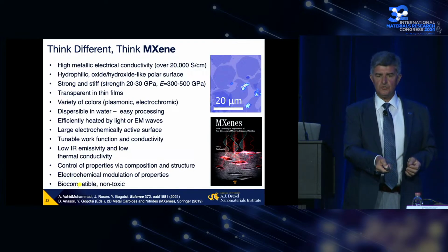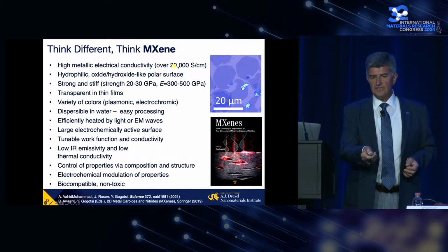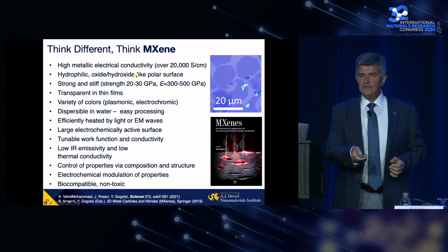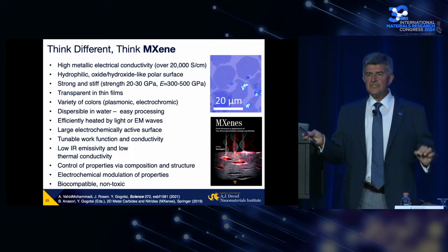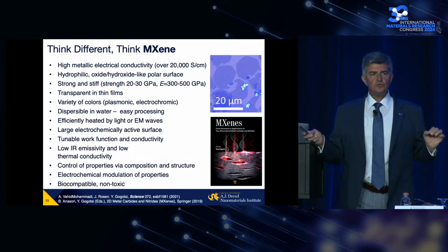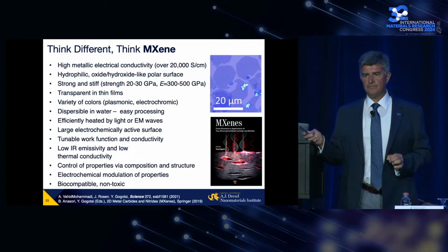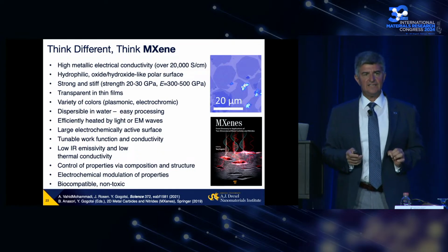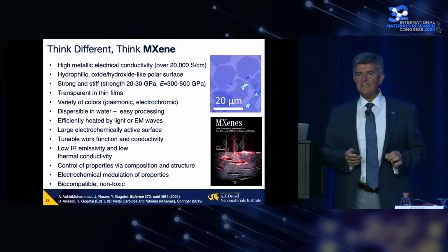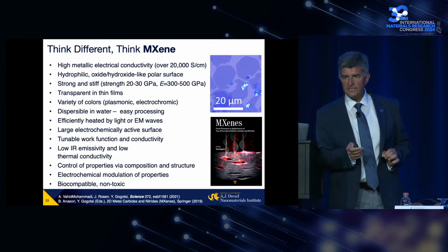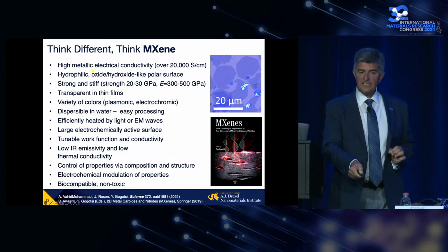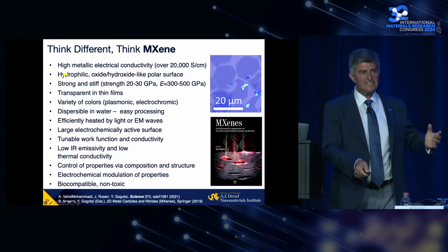A few things I already mentioned: high metallic conductivity. After drying, we get 20,000 Siemens per centimeter nowadays, climbing towards 30,000. If you take graphene oxide and reduce it at 400 degrees Celsius, you get 2,000 to 4,000 Siemens per centimeter - so it's an order of magnitude higher conductivity. Taking into account all the conductive inks and additives where people are trying to use graphene nowadays, it's a big application. It can be processed like graphene oxide from water, but conducts like graphene, even more, and surface termination doesn't kill its conductivity.